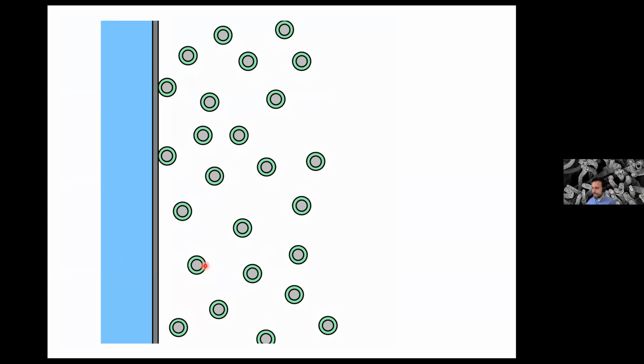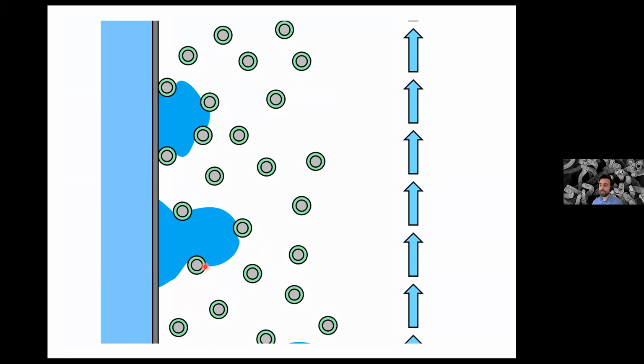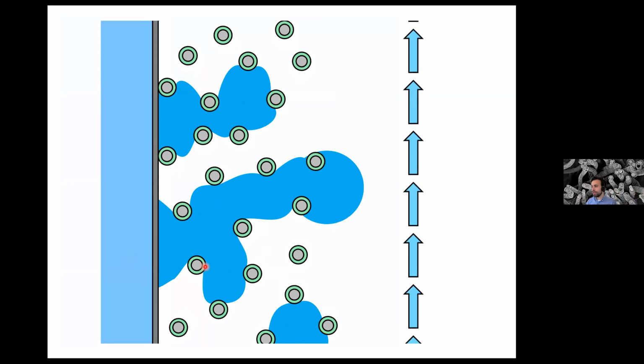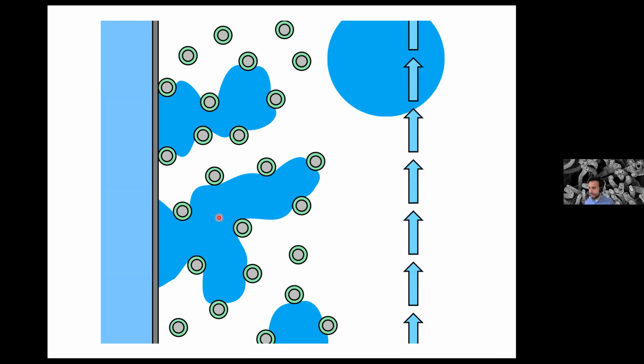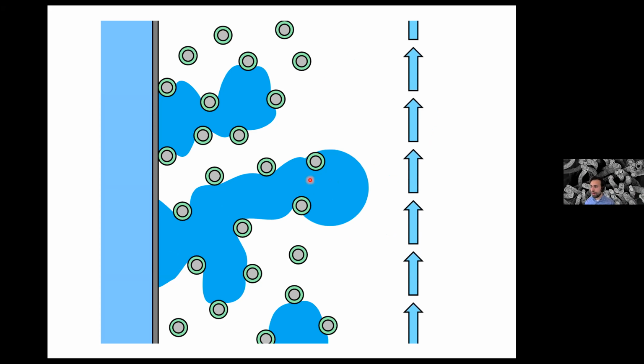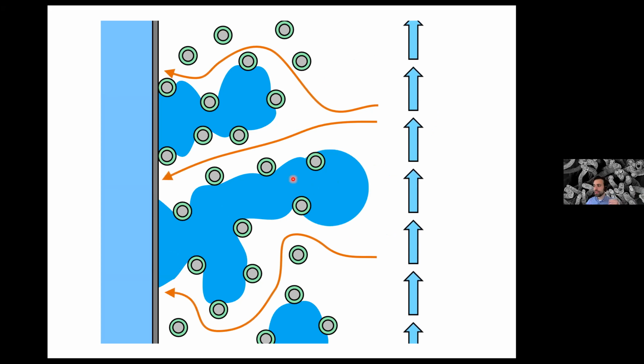Now we know from experiments and theory that the water at the micrometer scale will follow these tortuous paths, which are determined by the material microstructure and the local surface chemistry. Now, in chemical engineering language, this is what we call decreased effective diffusivity, because the gases are forced to travel longer distances, increased tortuosity, right? So how can we rethink this problem to try to channel the water and the gases in a way that they follow straightforward pathways at a micrometer scale?